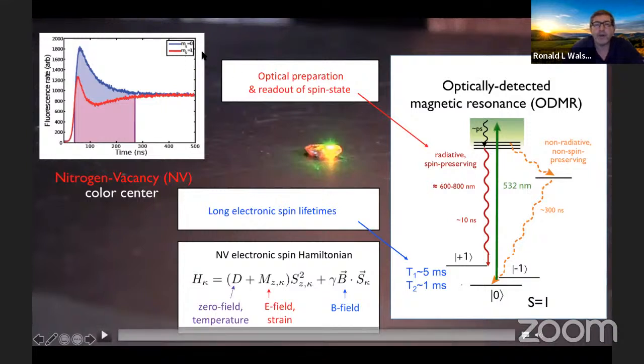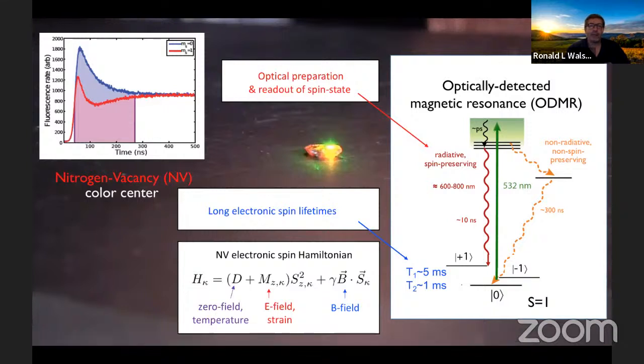In the red, you see starting in ms equals 1. Turn on the green laser at t equals 0, there begins to be absorption of the green light. The red fluorescence is beginning. It's starting to leap up just like you got with the ms equals 0, but then it hits a peak at a lower value and dips down. What's going on there is over the course of 100 or 200 nanoseconds, there's a probability to go through the second decay pathway, the non-radiative pathway that I told you about earlier. That has about a 50% probability. So on average, what happens is that the ms equals 1 level has a lower average fluorescence rate.